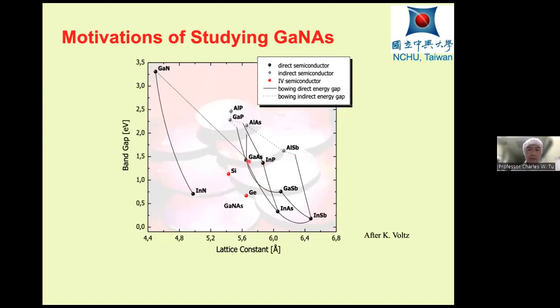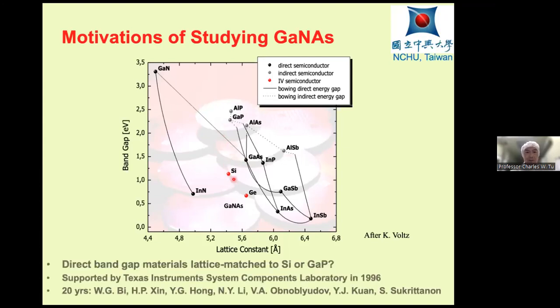The reason for looking into nitride or mixed arsenide nitride is that if I incorporate nitrogen, say 20% nitrogen, into gallium arsenide, I'm going to have a direct bandgap material which is lattice matched to silicon. Okay, so that's kind of attractive.